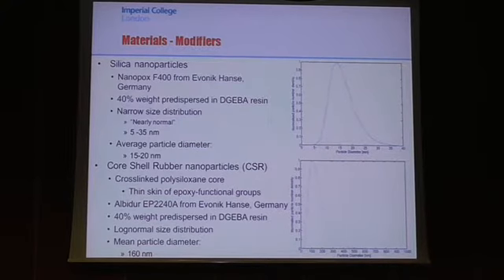The core shell rubber particles have a log normal size distribution. Here, the mean particle diameter is about 160, but we do see some particles up at half a micron, but not a whole lot of them. So these core shell rubber particles were also obtained pre-dispersed in the DGEBA resin, and they have a cross-linked polysiloxane core and a thin skin of epoxy functional groups on the edge. They're not really core shell rubber, they're more kind of core skin rubber. A lot of core shell rubbers have an actual PMMA shell, but these just have kind of a skin of functional groups on the end.